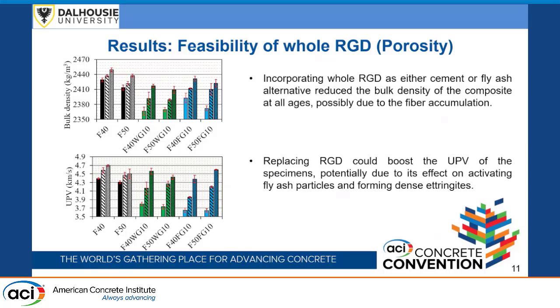So when we go for bulk density and ultrasonic pulse velocity, for bulk density, we can see the use of whole recycled gypsum has more effect compared to using fine recycled gypsum drywall. And we suggest that this effect could be because of the fiber accumulations, because RGD in its original form contains some fibers, because we just use the original one, we don't do any treatment. So we expect that the fiber accumulation could result in the difference between the bulk density of mix containing whole recycled gypsum and mix containing fine recycled gypsum.